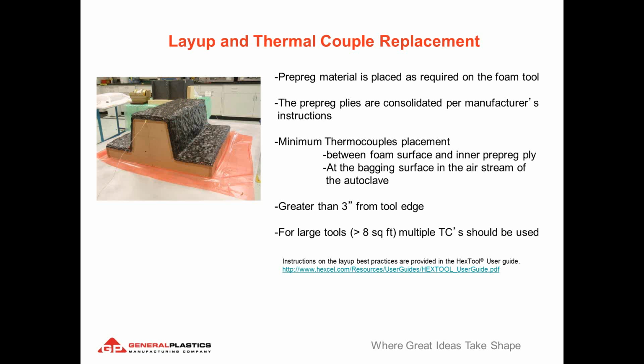Now, you also want to make sure your thermocouple is at least 3 or 4 inches from the edge of your tool to prevent any kind of edge effects. Also, for larger tools, more thermocouples are recommended. Every 8 square feet you should have a pair of thermocouples monitoring cure, and we also recommend that they are placed near the airflow of your autoclave, for example, or oven. And again, there are some much more detailed practices on the layup, which I didn't go into here at all, from the supplier Hexcel, and that link again is below.